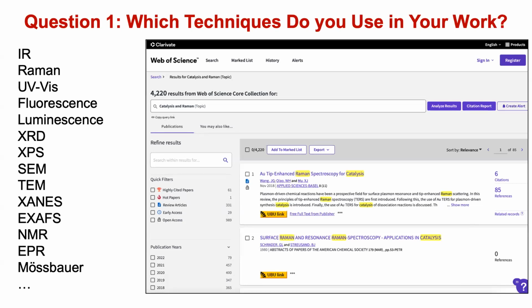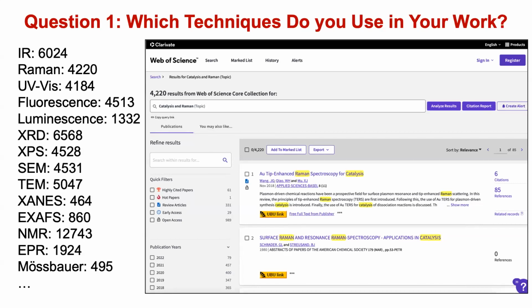Good. So maybe you're surprised, and I must say this Web of Science, it's always a bit tricky in the sense that it depends on what keywords you put into the system. But I just show you here what I did yesterday. What you find is actually a lot of NMR, but I think that has to do with the use of NMR to identify your molecules, not per se for the catalyst. A lot of infrared, Raman, vibrational techniques, I think. And you see certain things are a bit rare: EPR, it's really for the specialist. Mössbauer is completely limited to, as you most probably know, a lot of iron. And even synchrotron, although you have here your own synchrotron, is rather limited. That's most probably because you need a lot of expertise to go to a synchrotron to get something done there. And you have to have a beam time application.